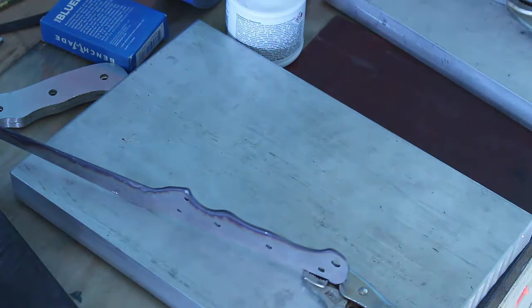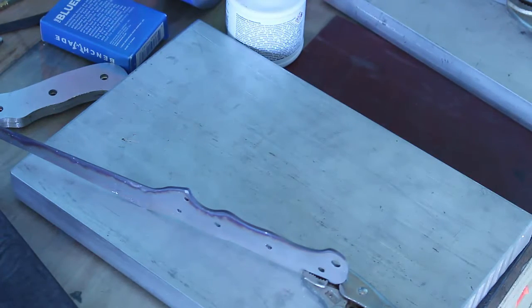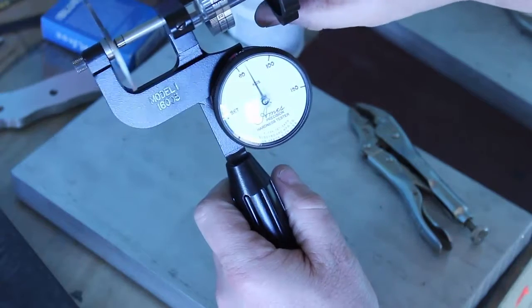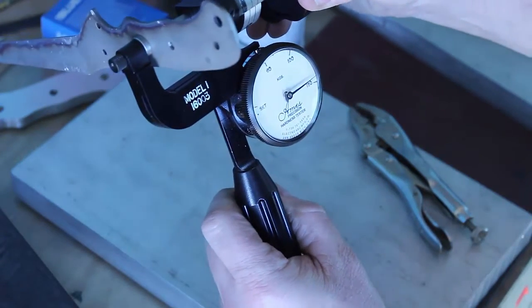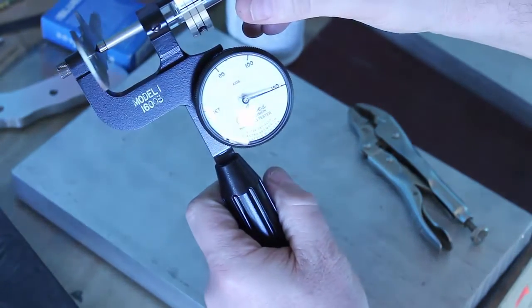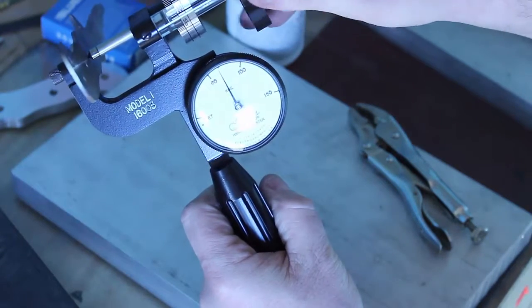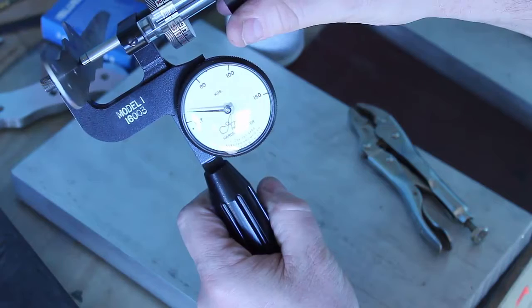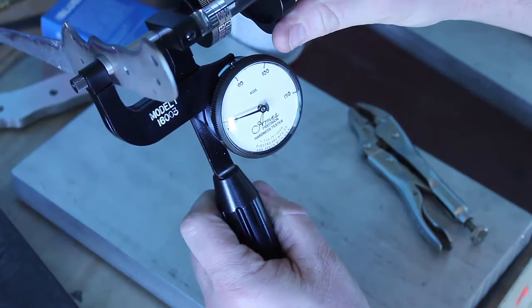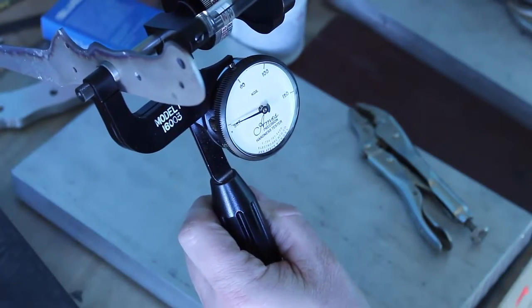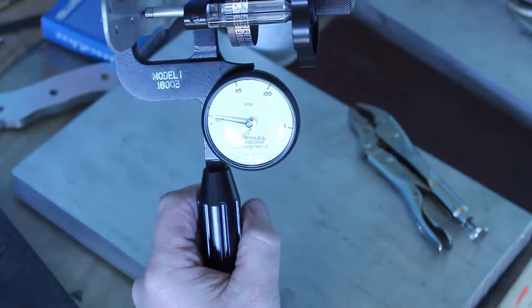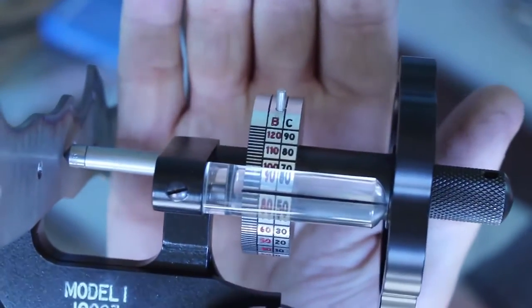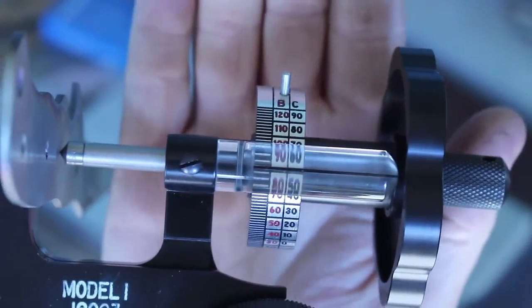Well, it's done with its second heat treat. Same thing with the second heat treat. It was 450 degrees for 2 hours. So we will check the Rockwell. See what we have. And again, bring it up to 150. And then bring it back to set. And right there it's reading 61. You guys won't be able to see that in that glass, I don't think. Something like that right there, 61.